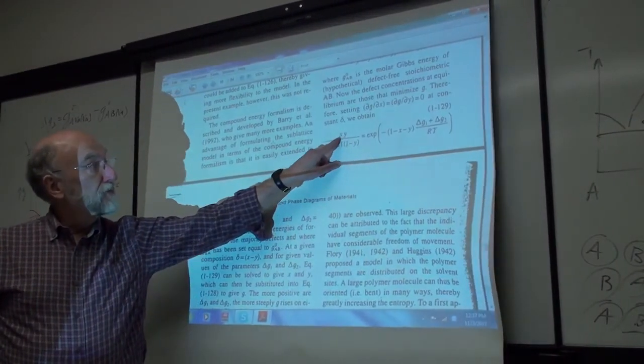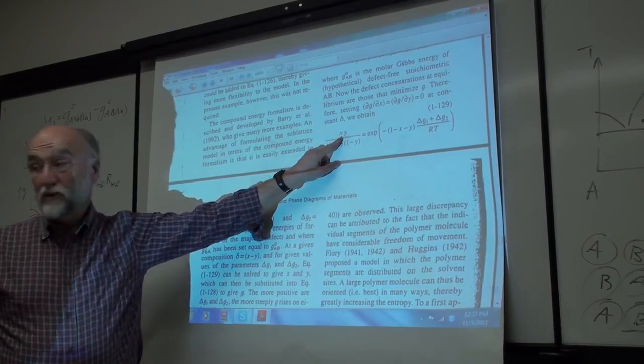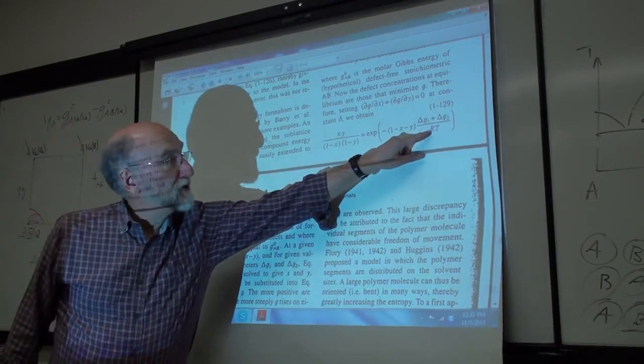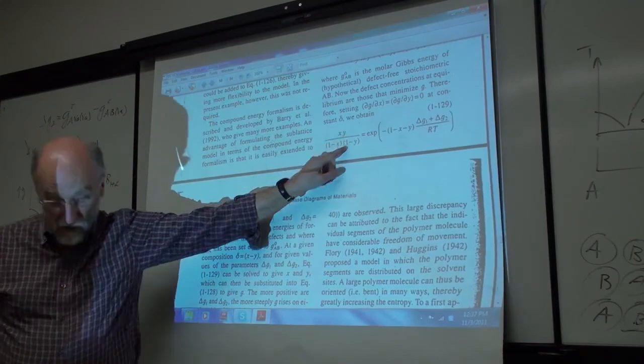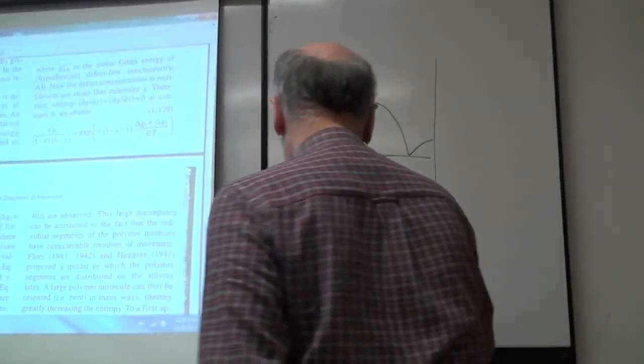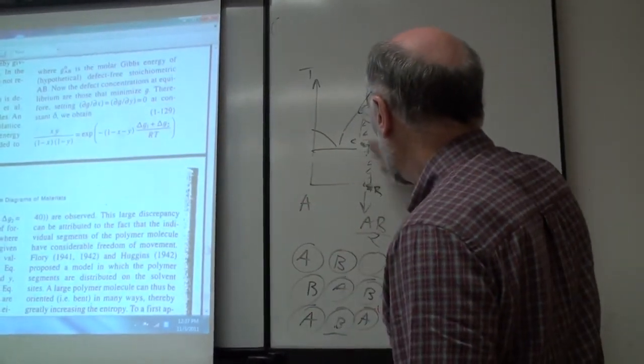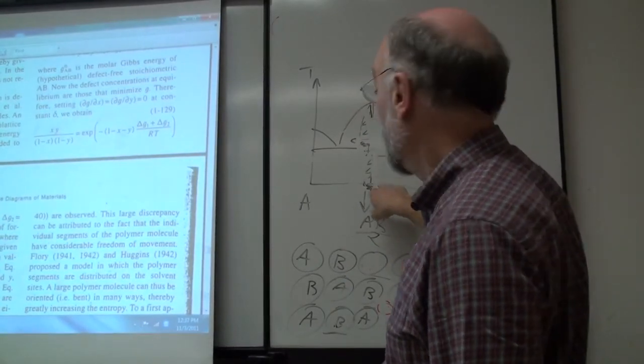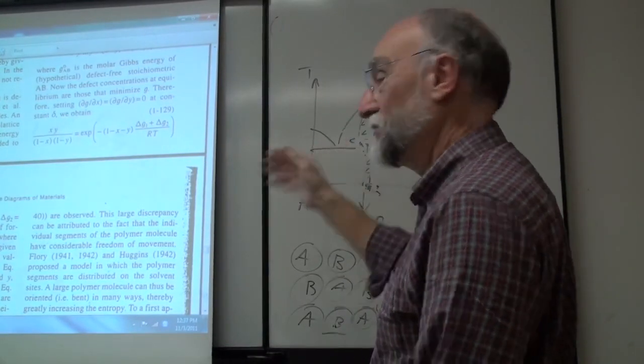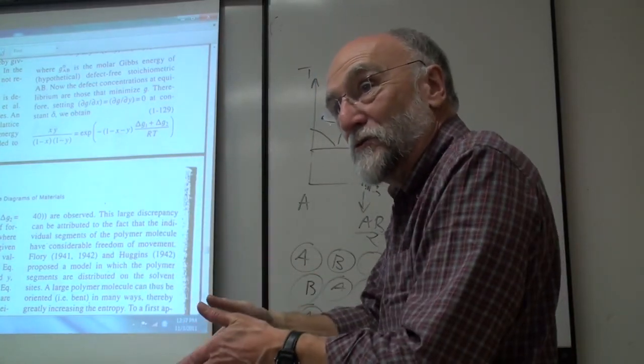But that's the thing, if you measure the enthalpy of formation of that compound, at which composition is your AB actually? Well, you usually measure the enthalpy at room temperature, and at room temperature, again, remember, it's another thermally activated affair. XY is a product of the concentrations of the majority defects. And as the temperature is very low, this XY product approaches 0. And that's why, if you see a phase diagram in which these phase boundaries come down vertically, it can't possibly be right, and they all come down. At room temperature, everything really narrows right down.